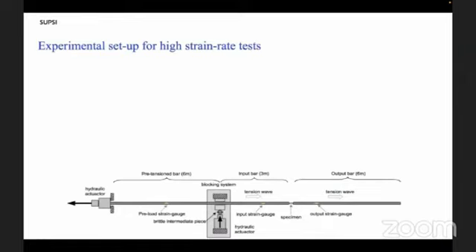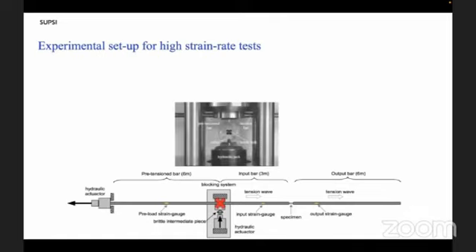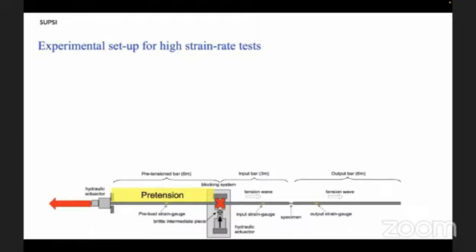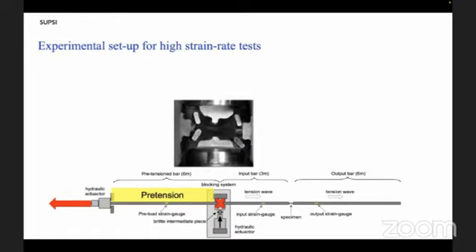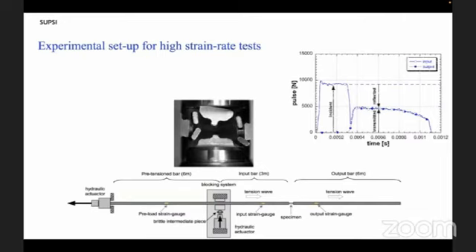The tensile testing at high strain rate was performed by means of a split Hopkinson tensile bar installed in our laboratory. The tensile bar is clamped on one end by a blocking device and the other is connected with a hydraulic actuator. It is possible to store elastic energy in it. The preloading governs the test velocity. The test starts by releasing with the brittle fracture of the bolts in the blocking device, so that the incident wave pulse propagates through the input bar, reaches the specimen, and at that point some part is reflected back and another is transmitted to the output bar.